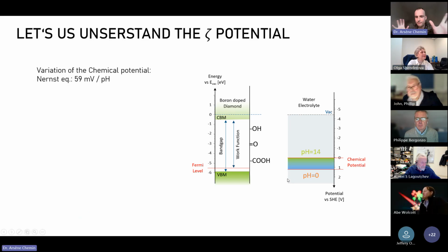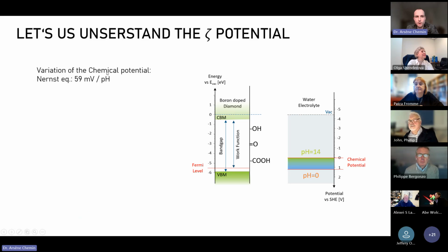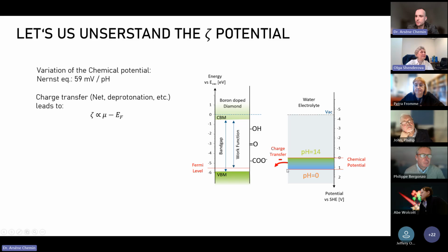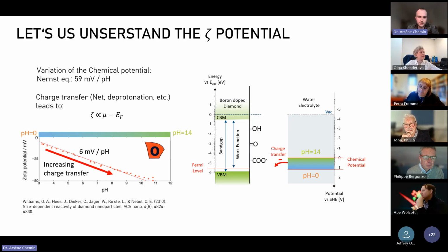So basically, you can understand everything by what I was saying. In the case of the oxidized terminated diamond, you will have a positive electron affinity. So the band will be quite low compared to the vacuum level. And if you put the numbers together, you will find out that the Fermi level in the diamond is likely to be lower than the chemical window of water between pH 0 and pH 14. That will lead to a charge transfer from the liquid environment to the diamond. And the usual chemical way we see that is by the deprotonation of acid group at the surface of the nanodiamond, leading to a negatively charged diamond. And that will explain the negative zeta potential and the evolution with the pH.